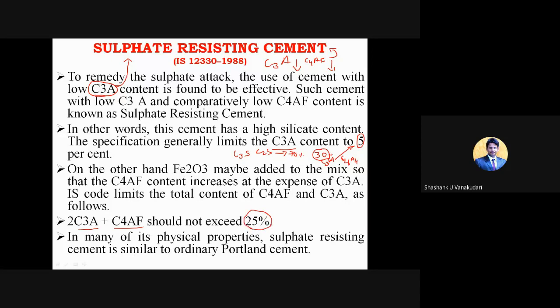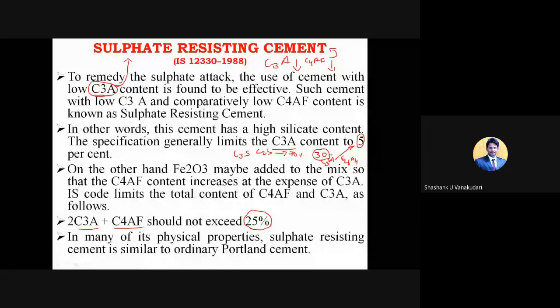sulfate resisting cement. In many of its physical properties, sulfate resisting cement is similar to ordinary Portland cement. The only thing is the percentage of C3A as well as C4AF should be less compared to ordinary Portland cement. Because these are the two elements, especially C3A, that is tricalcium aluminate. When this aluminate reacts with the sulfate content, it results in sulfate attack, right? So to overcome this, we need to reduce this content itself, so that sulfate attack may get reduced during the construction part.